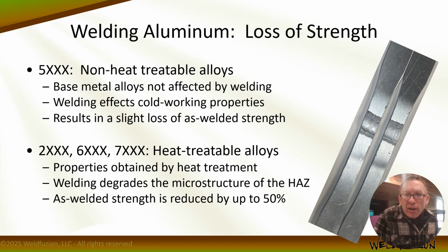Now, non-heat treatable alloys like 3000 and 5000 series don't see the same level of strength reduction after welding. The reduction is more minimal because these materials are not heat treatable; instead they're cold worked or strain hardened to achieve their maximum properties. And this is simply not as drastic of a change as heat treating in heat treated and heat treatable alloys. In the case of arc welding, heat can reverse the strengthening effect of cold working. And again, this is minor compared to the loss of strength in the heat affected zone that can happen in heat treatable alloys like 6061.